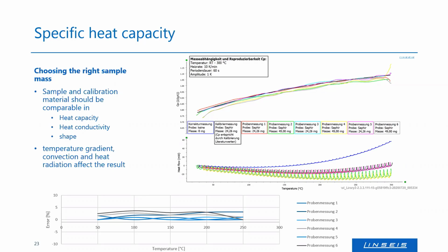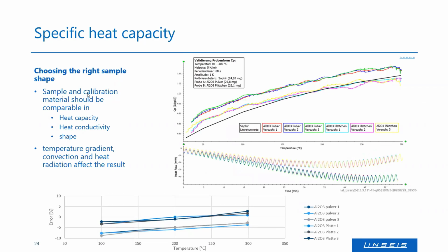And also, if the sample is too high, for example, if you use a polymer granule with bad heat conductivity, and it's, for example, 10 millimeters high, then you will receive a temperature gradient. But this I can show you on the next slide, I think, especially here. I've measured some different alumina samples. So there is the sapphire literature value here in this diagram, and I've measured against this sapphire and powder. So these are the upper curves with a big deviation here, and also with a plate of alumina. Alumina and sapphire are basically the same material, of course. Sapphire is just one big crystal of alumina.